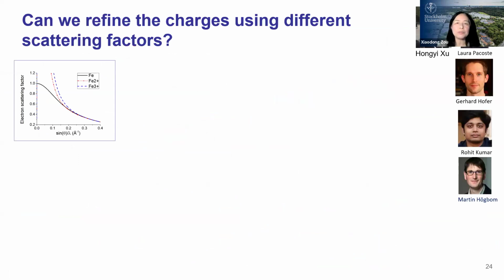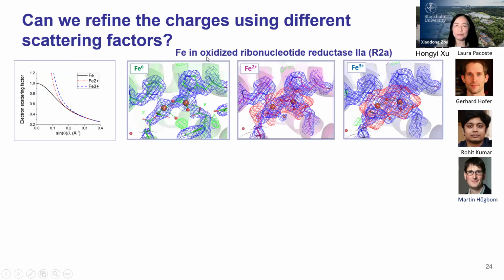The next one we want to show is to see how we can look at the charges, because if you use electron diffraction, you can see that this is iron zero, and they have charges. The scattering factors are very different, so it should be possible to determine the charge using electrons. We studied an iron enzyme, the oxidized ribonucleotide reductase R2A, as we call it, and we modeled it. This is the structure. We used scattering factors for neutral, 2+ and 3+ iron, and we found that actually the neutral scattering factor fits the map much better than iron 3+, even though this is the oxidized form. We know that it is.